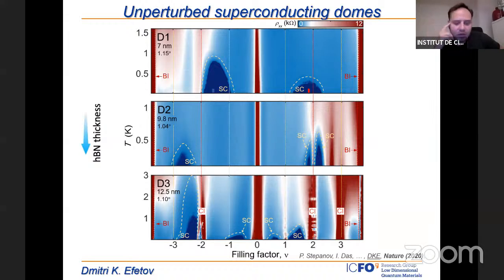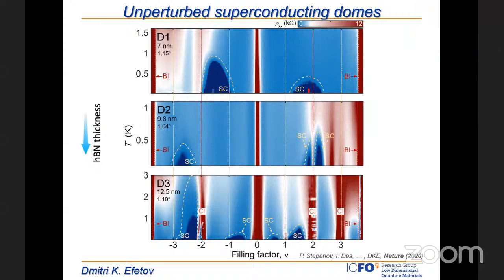And I think one way, of course, to take it is that this is exactly what you would expect from an electron-phonon superconductivity, that it just should not be affected when you change the dielectric environment, or it should be very weakly affected. But of course, there are many different scenarios people are debating. So superconductivity arising from correlations is not ruled out completely by these results, but I think it just enriched the debate a little bit. Okay, so I will now show a little bit of the topological results, probably the last thing I will show. If there are any questions about superconductivity, this is a good time to ask now.